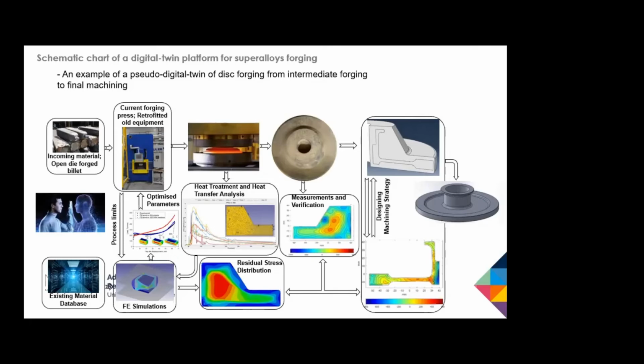So now we're at a situation where we can measure, we can predict, we can validate, but also once we're confident that we can validate, we can even be in a scenario where we can locally cool to make sure we can redistribute the residual stresses, which we have a project to do at this moment in time. But we've got to a scenario now where that may be the residual stress profile, tension, compression, whatever. We're now at a capability where we can develop, and we have developed, different machining paths to minimise distortion during the machining process. So we're now at a stage where we've captured enough information, we have enough fidelity in the digital ecosystem and the feedback during that system to locally quench such that we can get the optimum machining path to minimise distortion, therefore reducing the amount of rework in our final customers' parts.